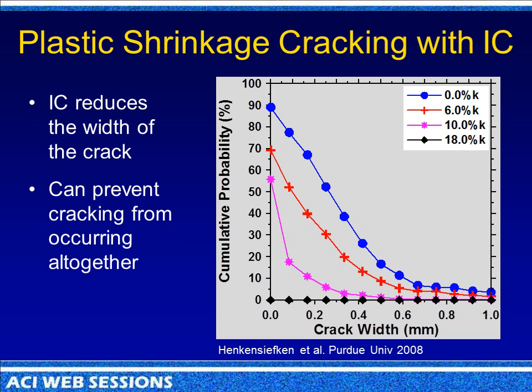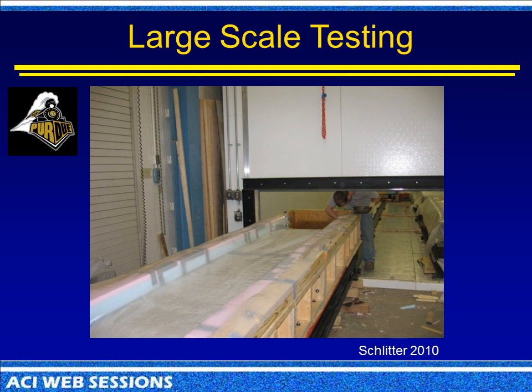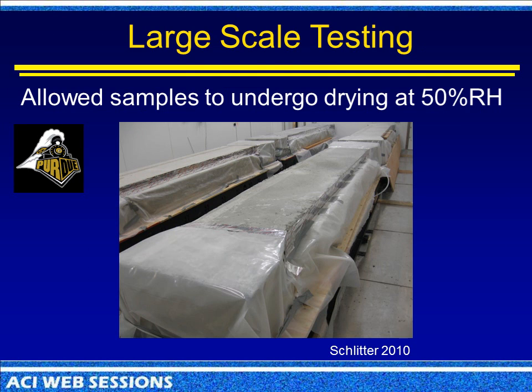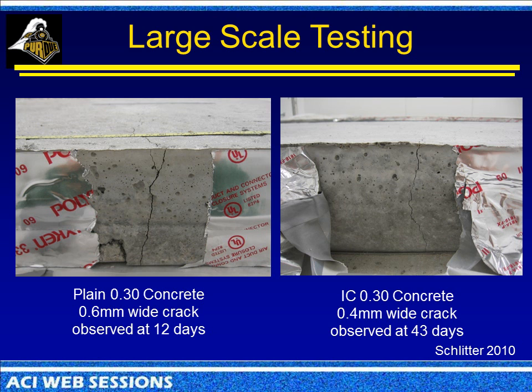And this is pointed out again here at Purdue. As you can see, as they get up to this 18% of the lightweight, you get 0 cracks at all. And as you get down, you start getting more cracks. And the one without any, you get a lot more potential for cracking. Now here's some real life, some big slabs they've done there at Purdue, big test sections, and you can see they fill these with concrete. And here's what's at 12 days, they got a 0.6 millimeter crack width, and over here at 43 days, so almost 4 times as long, they only got a 0.4 crack. And so this internal curing really shuts down the cracks.